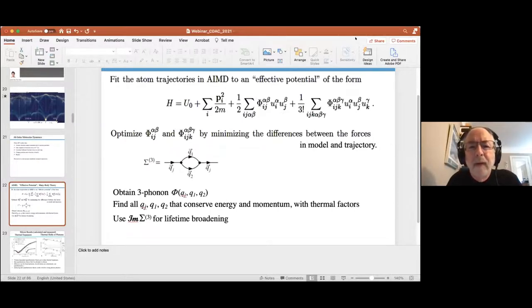To interpret it, though, we need to interpret these trajectories. And what we've been doing is use an effective potential method. We have a Hamiltonian that we fit to the behavior of the ab initio molecular dynamics. We have a kinetic energy, and then we have a potential energy, which has got the offset in energy, a quadratic term and a cubic term. And with the quadratic and the offset, we can also approximate the quartic by renormalizing the force constants for the quadratic. But an important part we get is this cubic term.